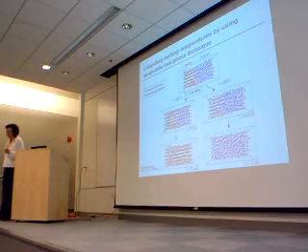So first of all, you look at the diffusion coefficient, whether the system is diffusive or not. This may not be your only criteria, because depending on what you are simulating, your liquid may be very viscous, and so the diffusion coefficient may seem to saturate and become very small, but still the system may be a liquid.